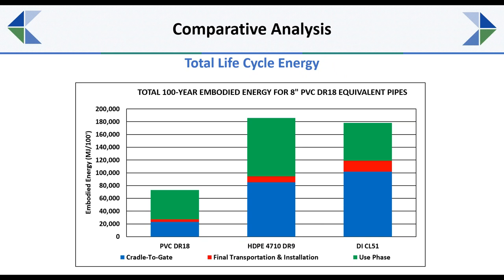So this next graph here just compares PVC, HDPE, and ductile iron pipes for the higher pressures, and what's the total embodied energy or the cumulative energy demand for the cradle to gate, so all the way up until the final transportation. Then it looks at installation. Then it looks at the use phase. And so what you see from there is that PVC pipe has approximately 60% less total embodied energy than either HDPE or ductile iron for this 8-inch higher pressure or higher flow condition.